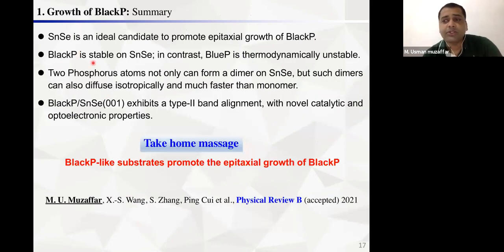So this is the summary of the first part. SnSe is an ideal candidate to promote the epitaxial growth of black P. Black P is stable on SnSe, while blue P is thermodynamically unstable. Then two phosphorus atoms not only can form a dimer on SnSe, but can also diffuse isotropically and much faster than a monomer. And the black P-SnSe heterostructure exhibits a type 2 band alignment with novel optoelectronic applications. So the one-liner statement is that a black-P-like substrate promotes the epitaxial growth of black P. Actually, initially we submitted this paper to PRL, and we did fight with the referee for almost 1.5 years, and eventually it was published in PRB.